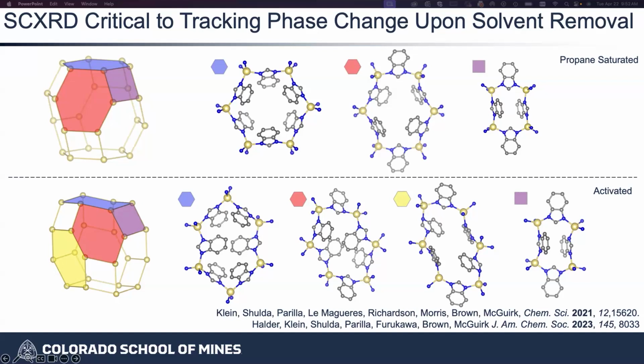But then when we remove all the solvent out of the system, it basically relaxes on itself. So you get a distortion of the coordination lattice, but it retains all the connectivity. But really what you see here is that those linkers are rotating from being kind of open to being very clearly CH-pi stacked. And so you have basically a gating phenomenon going on in these pores.